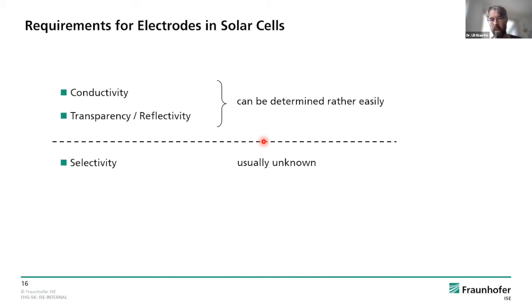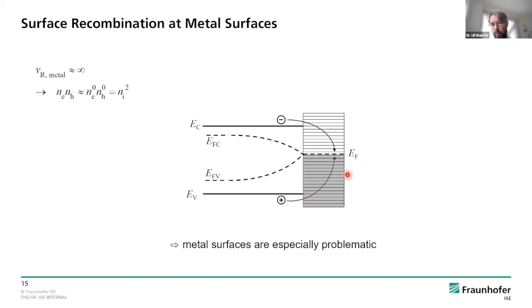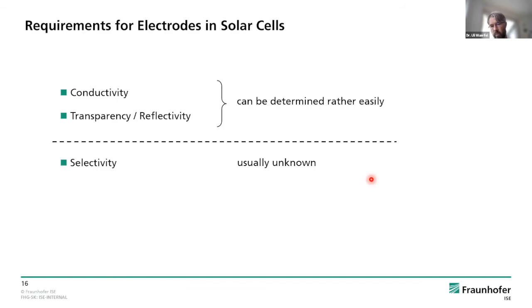Good. This brings me to more consideration about the requirements for electrodes in solar cells. Of course, electrodes have optical and electrical properties, like, for example, conductivity, transparency, and reflectivity, which have to be very good, but these can be determined rather easily. But the selectivity, like, for example, putting some metal here, how does this increase or decrease the rate of electrons and holes which are lost by surface recombination? This is usually not known. It's harder to measure. You cannot measure it directly.